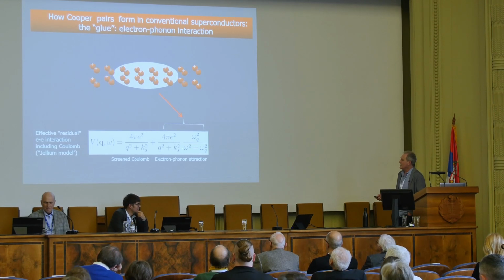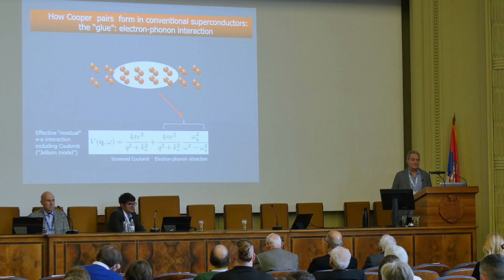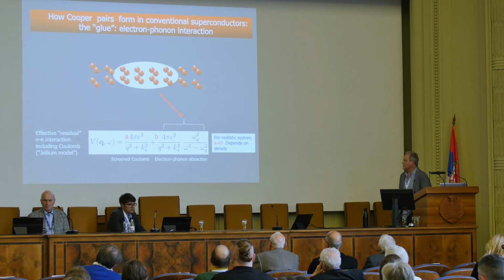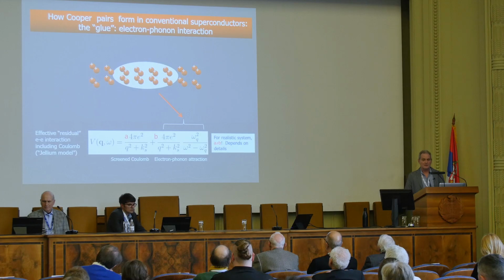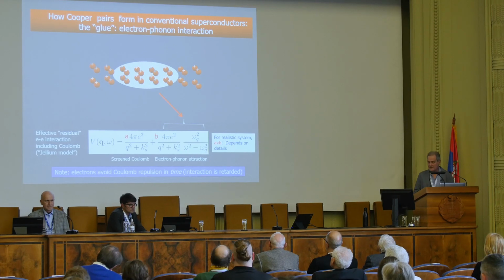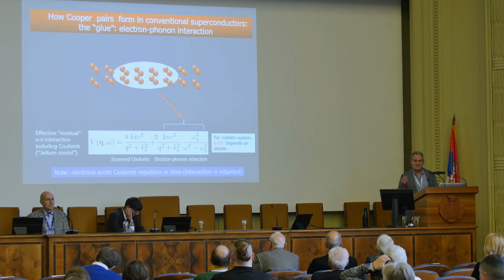Now, if you notice that when omega goes to 0, these two terms exactly cancel each other. And so you would think there's no interaction whatsoever. And all that means is that we haven't actually examined the details of the system very carefully. And if we do so, then you see that those terms are still there, roughly speaking, but they're weighted slightly differently. And so you can have a material which is a superconductor or one which is not a superconductor, depending on very small differences in details. I do want to note before I go on, because it's important for later, that the whole mechanism that I've described here depends on the electrons avoiding each other in time. They're at the same point in space, but not at the same time.